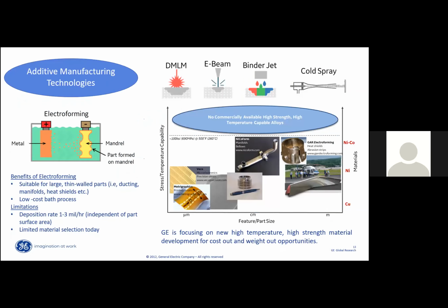One other project I'm leading, this is my last slide, is on material development for electroforming. Now, electroforming is also a kind of electrodeposition. It's very similar to electroplating, but what you do here is you have the metal or alloy that you're plating, you put it on a mandrel. We don't call it a substrate, we call it a mandrel, because after the process is complete, when the metal or the alloy is coated, the mandrel is removed. So now you have a freestanding article with the shape of whatever mandrel you put in the bath.